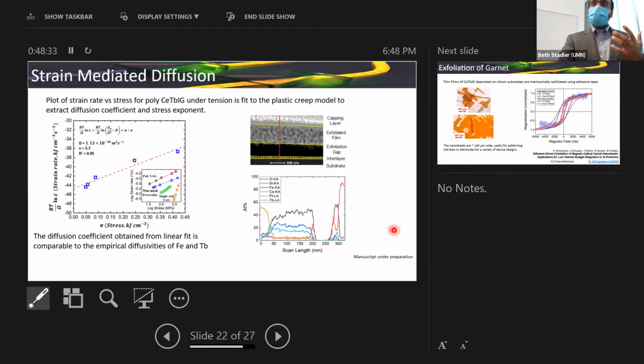You also have this interlayer, which forms as a consequence of some atoms diffusing towards the interface while the vacancies diffuse away from it. The presence of iron and terbium at this interlayer confirms that indeed the vacancies created by those cations is driving the exfoliation process.